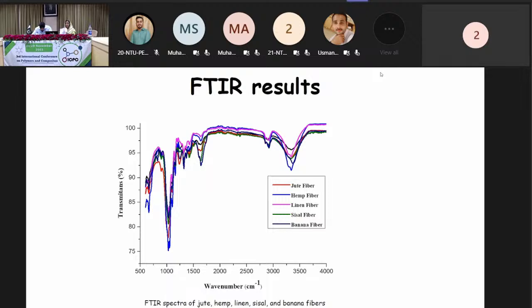The carbonyl C=O stretching vibration of carboxylic acid in lignin, or the ester group in hemicellulose, causes the peak at 1639 to appear. CH2 symmetric bending in lignin, cellulose, and hemicellulose, and CH symmetric deformation of cellulose and hemicellulose, are related to the peaks near 1427 and 1369 respectively.